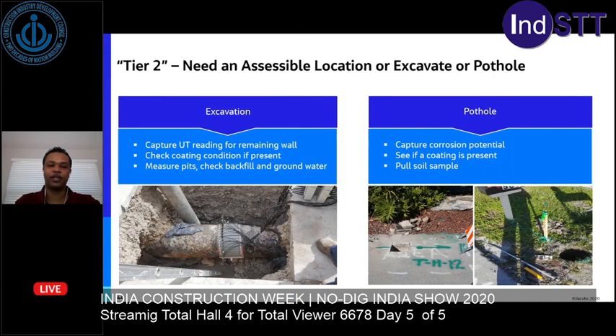So tier 2. With tier 2, you will need an accessible location. So you may have to excavate or pothole to get access to that structure. Within the excavation, you can capture ultrasonic thickness readings to see what the remaining wall thickness is on that asset. You can check to see if there's a coating present. You can measure the depths of any pits that may be found on that pipe surface. And also you can check the backfill. You can check for pH. You can send off the backfill for analysis, to see what the chloride, sulfate content, and redox potential may be within that backfill. And also you can check for groundwater.